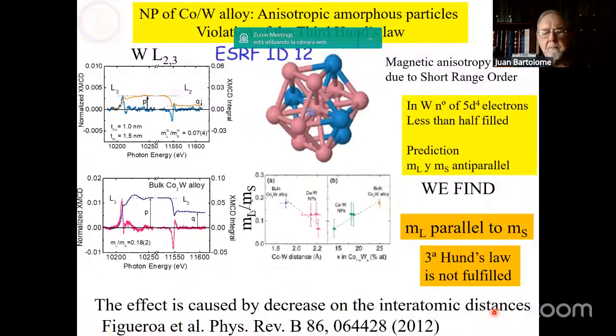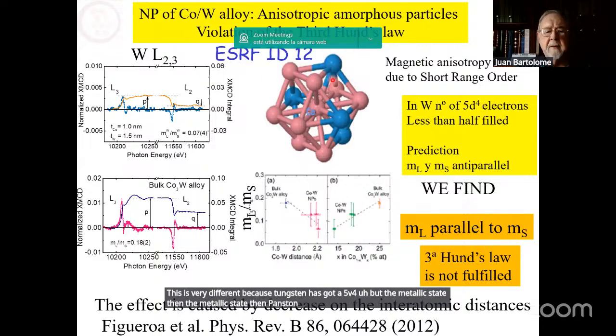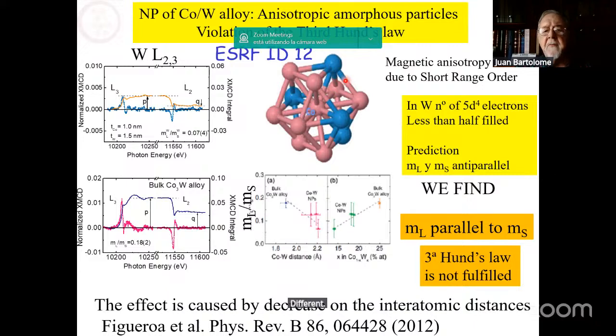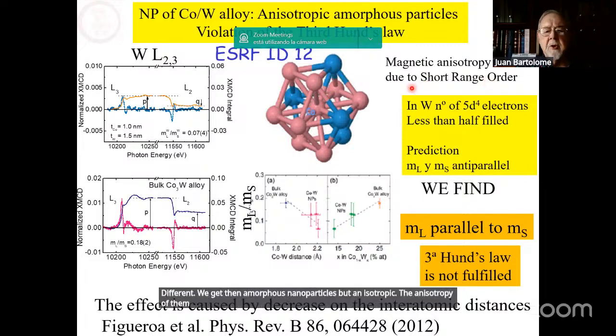But then we sputtered tungsten. This is very different because tungsten has a 5d4 band in the metallic state. Then tungsten enters into the particles. It doesn't remain at the surface. It enters and substitutes several cobalt atoms, so that the number of neighbors of each cobalt is now different. We then get amorphous nanoparticles, but anisotropic. The anisotropy of them is due to a short range order among the cobalt atoms within the particle.